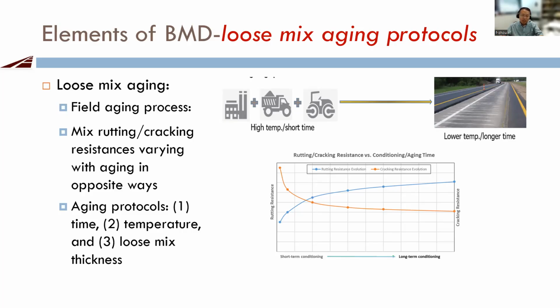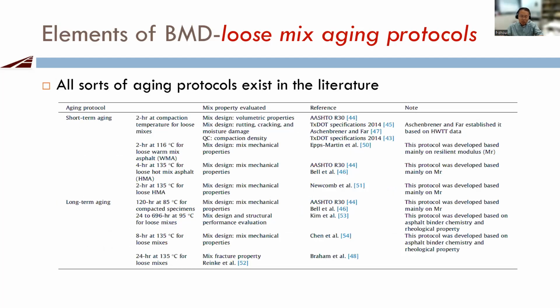Another reason why the aging is so important is that without specifying the aging protocol, we can actually make the mix pass any criteria you set. Because again, if I want to pass my rutting criteria, I can cook my mix a little bit longer in the oven. If I want to pass the cracking criteria, I probably, after I mix it, can directly compact the specimen and test it. So really, aging is extremely critical for performance tests, specifically for the criteria we're going to set.